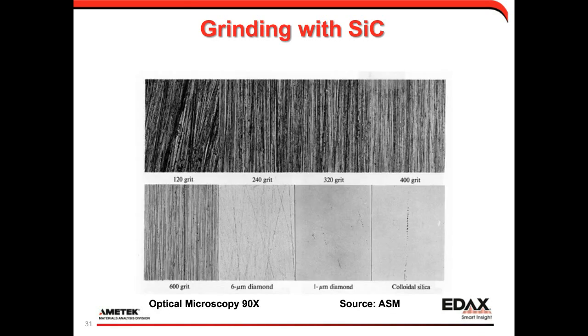This is just a classical image showing that at each step, you see that the grinding marks with each decreasing abrasive size become smaller and smaller until, as you get to some of your final steps with diamond, the scratches go away. And that's what we're aiming to do with polishing down: the feature size of the damage introduced with the different size abrasives becomes smaller and smaller. But I'll show some examples of how, even in these areas where we can no longer see them optically, we can still detect microstructural changes being introduced using EBSD.